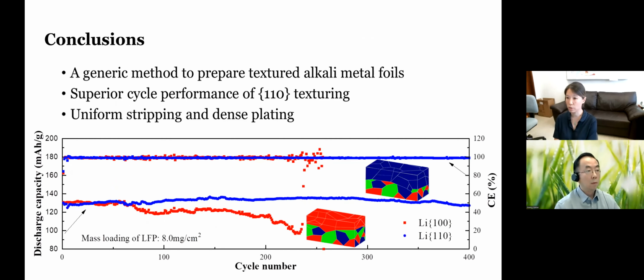So to conclude, I hope I've shown you that we developed a generic method to prepare the textured alkali metal foils. And we did obtain superior cycle performance of the 110 texturing, and that is understood by the uniform stripping and dense plating associated with such a plane with a thermodynamic origin. And of course, this is an ongoing project.